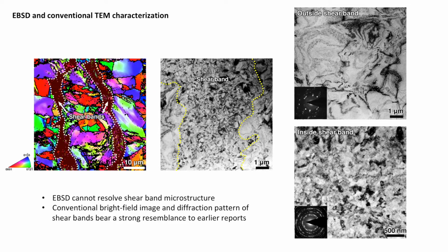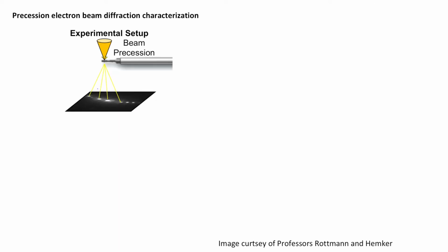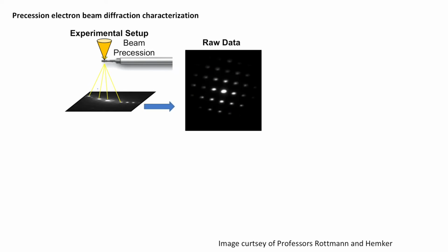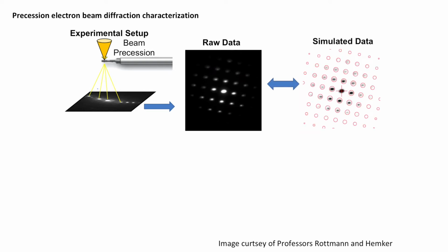In order to have a closer look at the shear band, we used a technique called precession electron diffraction, PED, to further characterize the microstructure of the shear bands. In PED, there is a beam that precesses on the specimen, and underneath the specimen, we collect the diffraction pattern. The beam also rasters on the specimen, working on the same principle as SEM or STEM. The signal is collected pixel by pixel. For each pixel, we collect the raw data, and the raw data is compared to simulated data to give us information on the crystal phase as well as the crystal orientation.